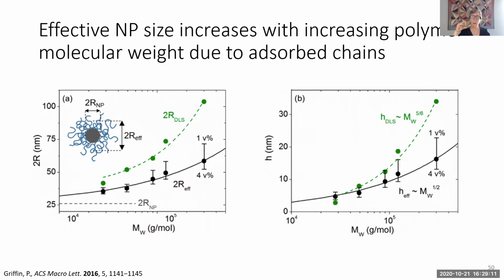So the strong interactions between the polymer and the particle create this bound layer, and that whole entity moves. So if we can use the Stokes-Einstein equation to extract an effective radius. So this is the bound layer and the bare particle. The bare particle, of course, is molecular weight independent, but the bound layer, this effective diameter of the particle, increases with molecular weight. And if we just look at H, which is the difference between the particle size and the particle and bound layer, so it's just the bound layer thickness, it increases as the molecular weight to the 1/2.